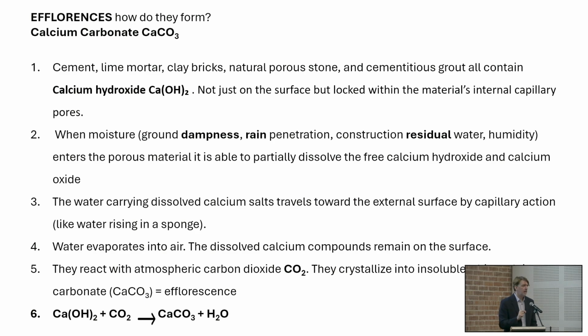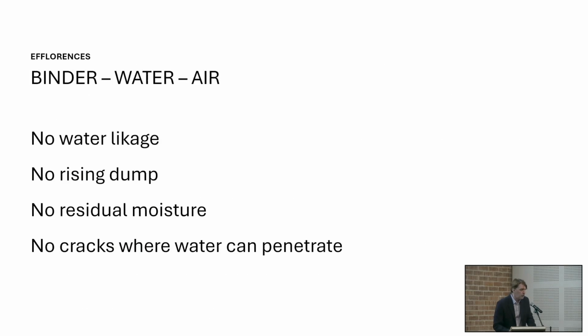The problem is I haven't considered the water. I put too much water, or I didn't block the rising damp from the ground. In all these cases, you are allowed to expect to have white spots on the surface, in industrial or residential application too. So what can we do, if the white spots come from the binder, come from the water, come from the air? Of course we cannot do anything with the air.